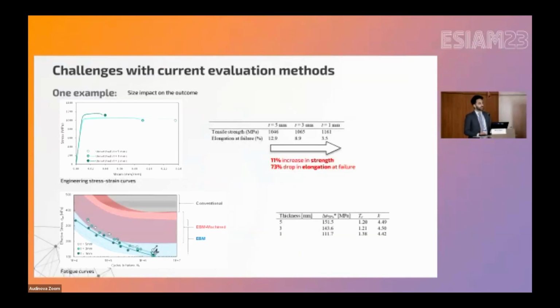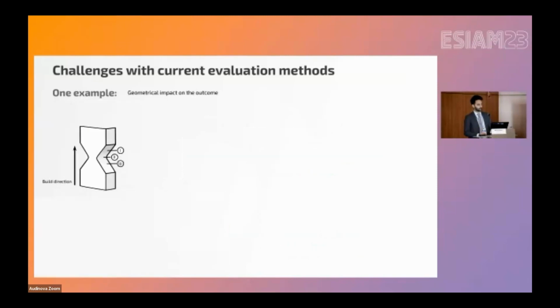Similar type of test was performed for fatigue. We could see that from 5 millimeter to 1 millimeter thickness, there is 27% drop in the fatigue properties. Okay, so clearly there is an impact on mechanical properties based on the scale that we had.